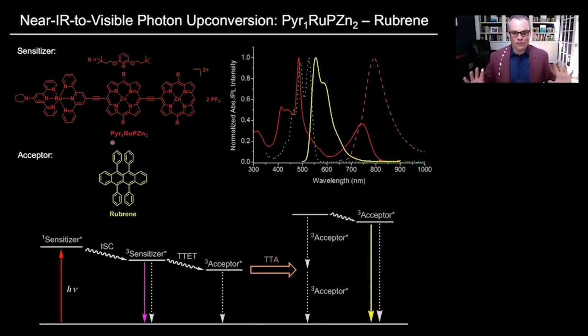Of course, we started to work with Mike Therien at Duke University, and Mike makes all of these beautiful donor acceptor compounds. If you'll notice, it has porphyrins built into these MLCT photosensitizers, all in the same molecule. Without getting into all the fundamental photophysics, this red line here is the absorption spectrum of that compound. There's all of this wacky intensity borrowing going on, but the idea is that this is the low energy absorption band, which now spans into the near infrared, and it generates this singlet fluorescence. Believe it or not, it has a low energy triplet state, but it generates singlet fluorescence, which is crazy in our opinion about these things.